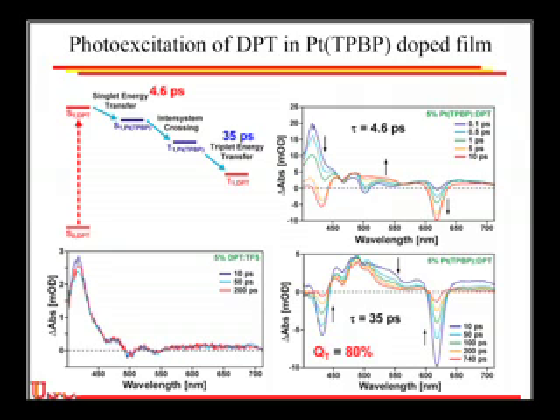So with a time constant of about 4.5 picoseconds, energy transfers from the singlet of DPT to the singlet of the platinum porphyrin. If I now wait, it goes through the same exact process as before. Once I'm in the singlet of the platinum porphyrin, it's a 35 picosecond time constant to get to the triplet on DPT with about the same yield. So we've tracked this out, so we know it takes 4.5 picoseconds to get from DPT to platinum porphyrin, and 35 picoseconds to get back to DPT again.